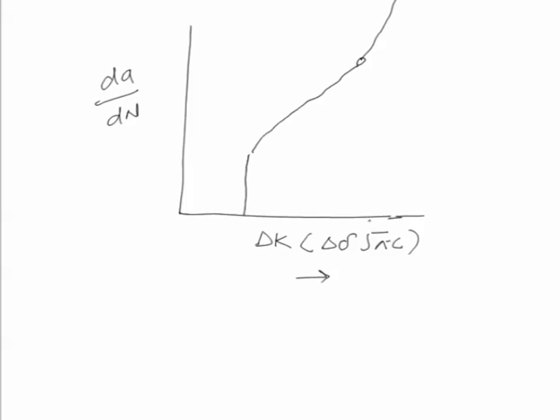The crack growth rate increases continuously. This is the first stage, and this is the second stage, where the crack growth rate versus the stress intensity factor range has a largely linear relationship. In the third stage, the crack growth rate increases at an increasing rate, which is clear from its positive slope, while in the second stage the slope largely remains constant.